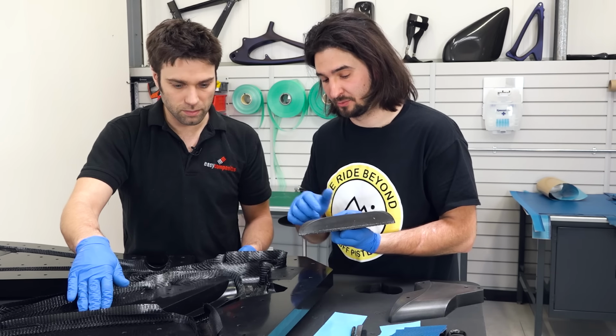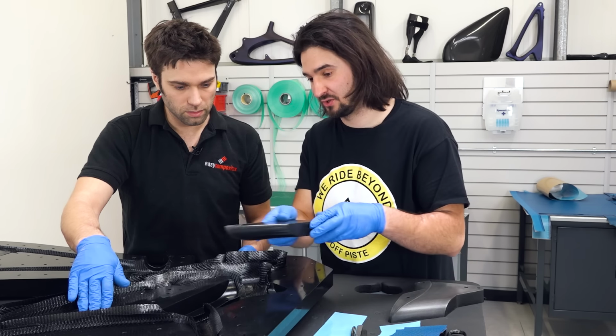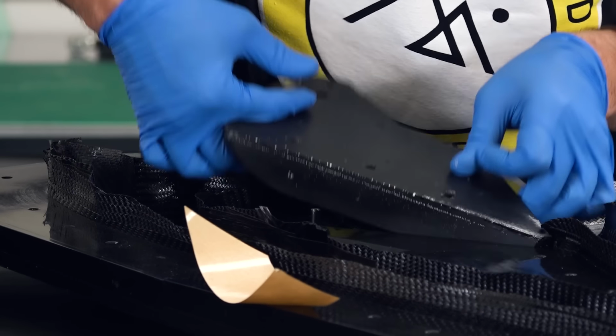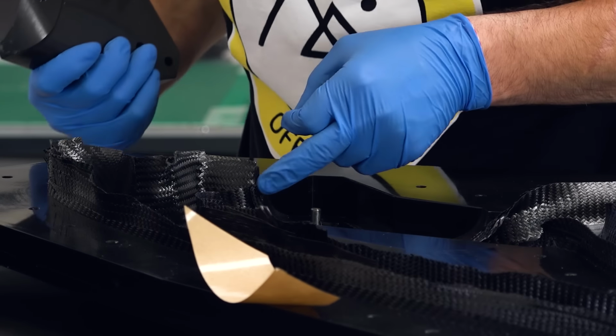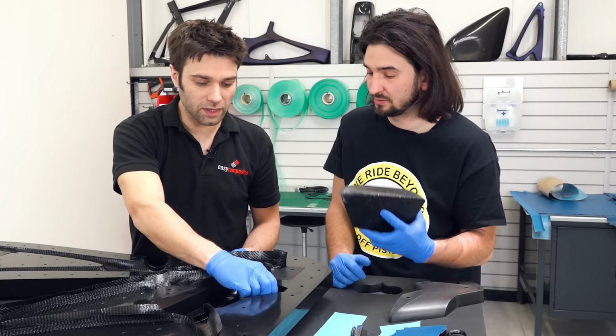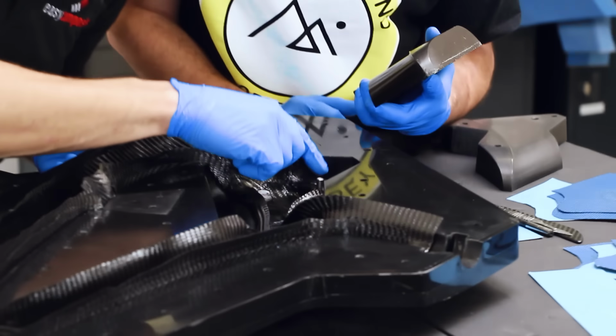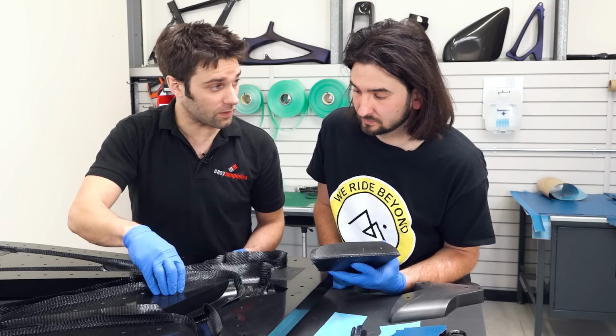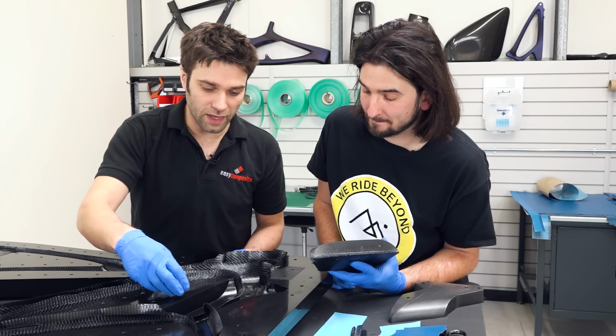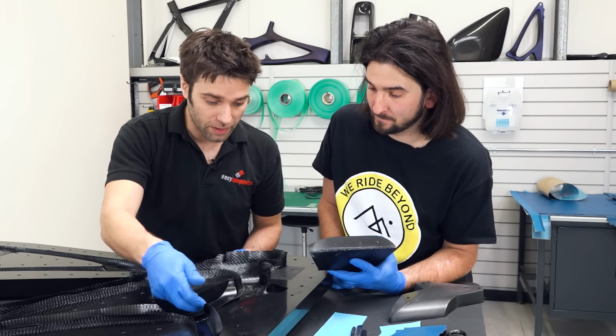Yeah, they do need laminating, but the reason why they're not laminated is that I had to check again a few times if the compression mould area is alright and if the laps actually open correctly, and we don't want them overlapping on each other. So where the linkage mount is, that's a solid laminate in there, very much the same as around the actual shock mount here. And then this section here will have a vacuum bag pass through it.